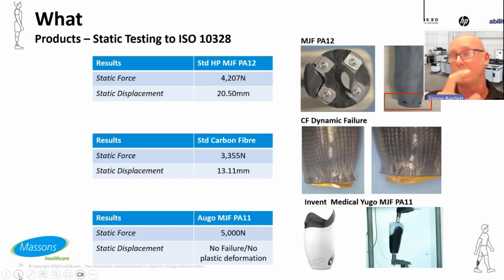Comparing that back-to-back test to what Invent Medical have done: they took that Augo socket and tested it to the same test. They stopped at 5,000 newtons, which is effectively the maximum testing strength of the testing apparatus. It didn't break. The closest thing that broke was actually the testing apparatus itself. We didn't see any failures. There was no plastic deformation, so no permanent deformation, and afterwards the socket was still fit for purpose.